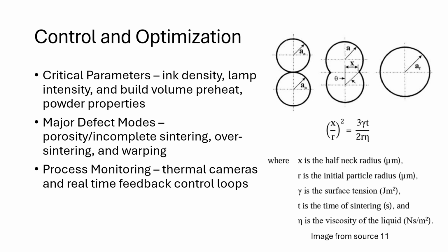The heart of consistent high-speed sintering printing is rooted in process control. The main parameters defining part quality are ink density, lamp intensity, powder properties, and chamber preheating temperature. Ink density dictates how much infrared energy the powder absorbs. Too little ink and heat absorption gives poor fusion where very little necking occurs. Too much causes over-sintering, resulting in surface finish problems.